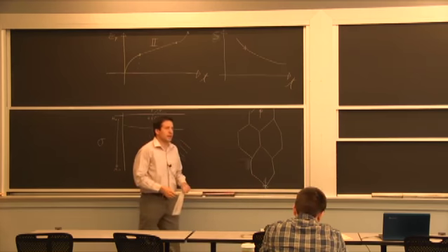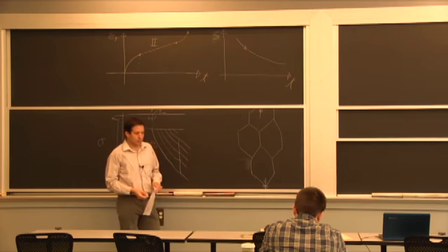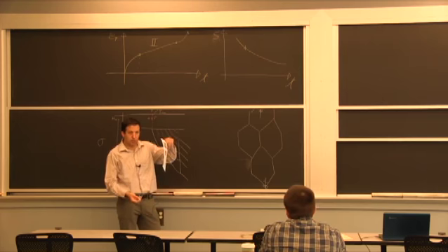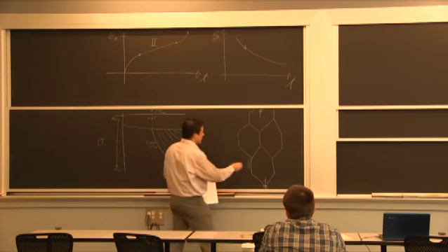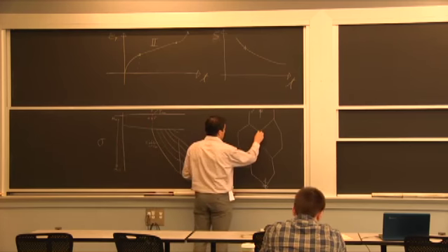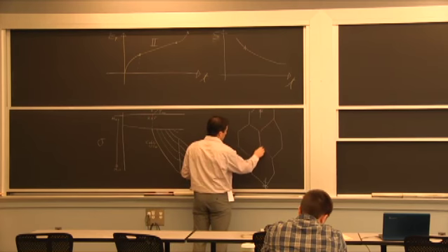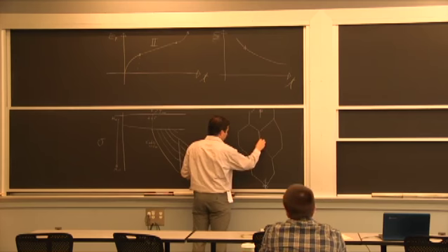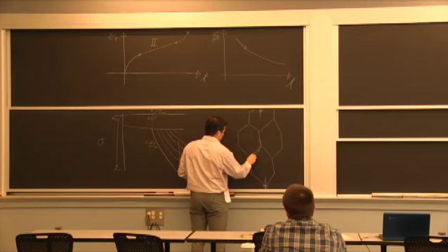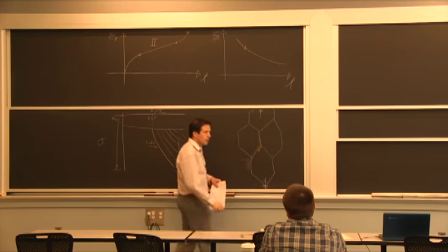One way that the material will stretch over time is by moving some of the atoms that are on this grain boundary and then move them to the other grain boundary. And that's our Coble creep.